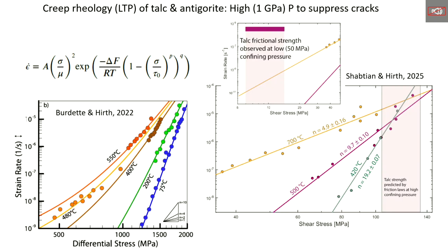And so she concentrated on that and found really good evidence for the low temperature plasticity in talc. But I want to emphasize some aspects of her data that are really important. The coefficient of friction of talc is really low. It's like 0.1. So if you go up to a gigapascal, the stress you need for frictional slip is in the range of like 100 to 140 megapascals of shear stress. And all of her data at that point clump up into one kind of cloud. And there's evidence that that is probably frictional, and there's not a strong temperature dependence to the friction at that point. But by being able to go to low stresses, she sees this really systematic temperature dependence.